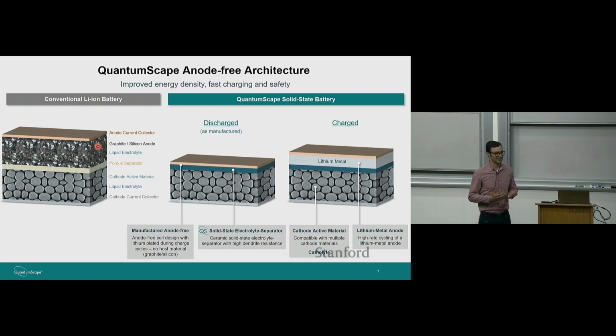That sounds simple. It's not simple to do because a lithium metal anode is not compatible with these porous polymer separators. What happens is, as you charge the battery, lithium will grow through the pores of the separator and create an internal short circuit. So there have been people who've tried for decades to solve this. It's a very difficult challenge. The approach we've taken is to replace the porous polymer separator with a fully dense ceramic material. And that in many ways is the core innovation of our technology.